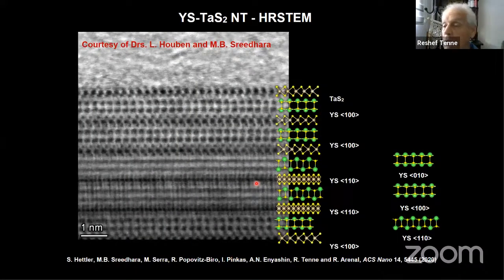If you go to a close-up of the structure, now it's not a cross-section. This is yttrium. It's an example of another study on yttrium sulfide, tantalum disulfide. Here you can already see all the layers, all the atoms. You see the yttrium atom is here, the sulfur atom is aside, and here is the tantalum disulfide. You see the sulfur atoms, and this is very important information on the structure of these materials and the nanotubes. From this, we can calculate the properties of these nanotubes, and we find that they are semi-metallic and they have some other interesting properties. We study them now in greater detail.